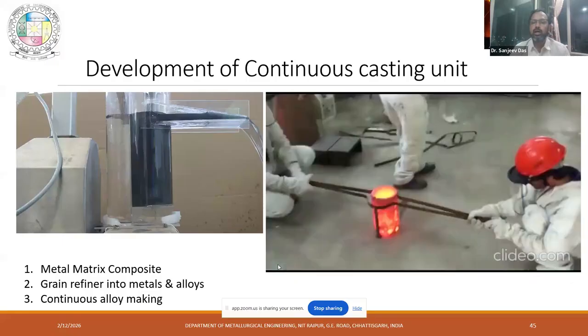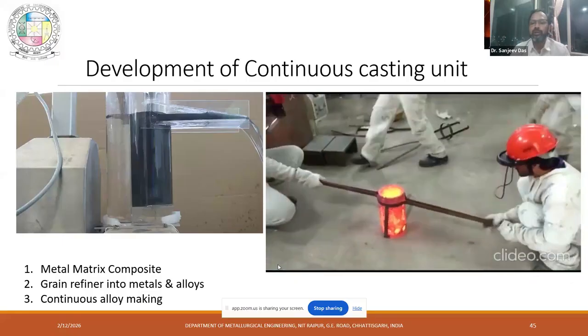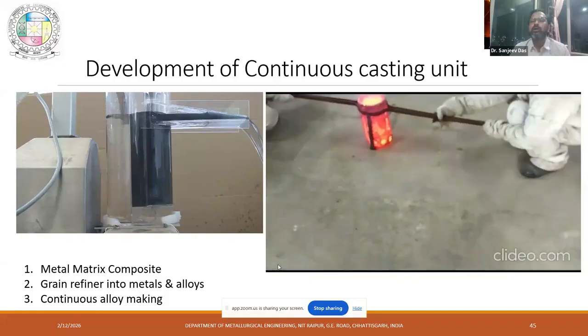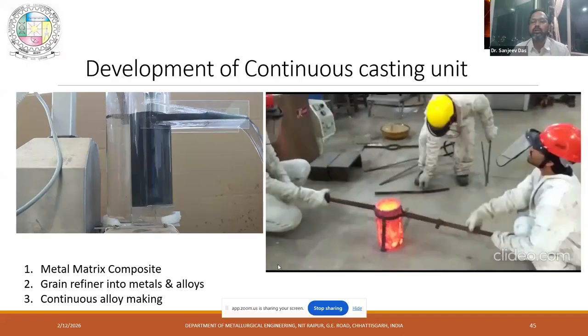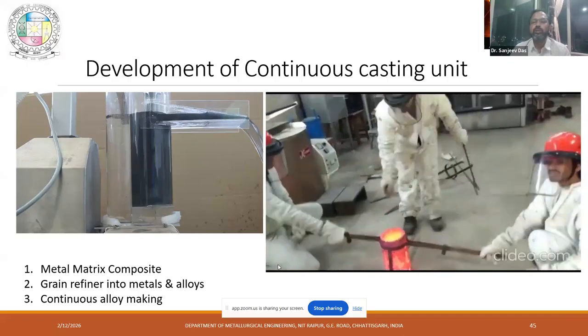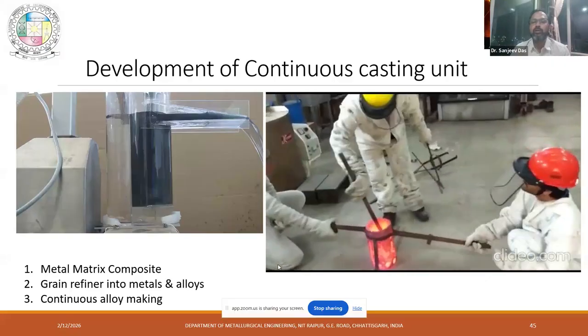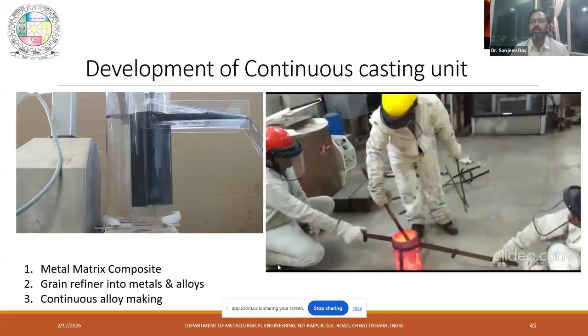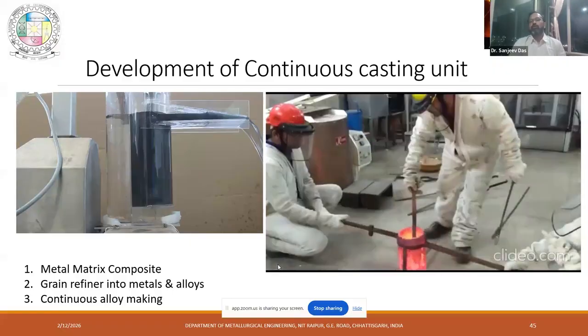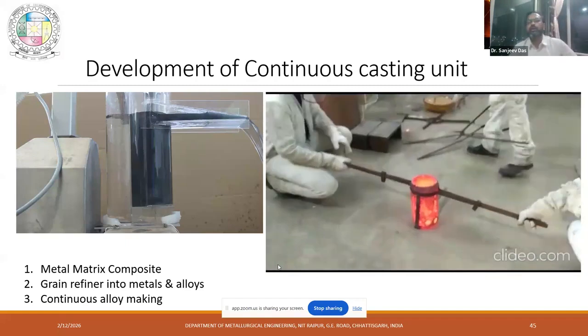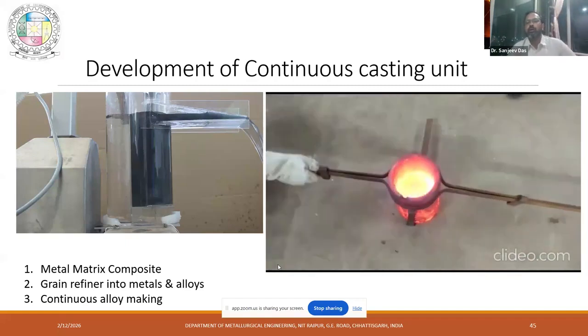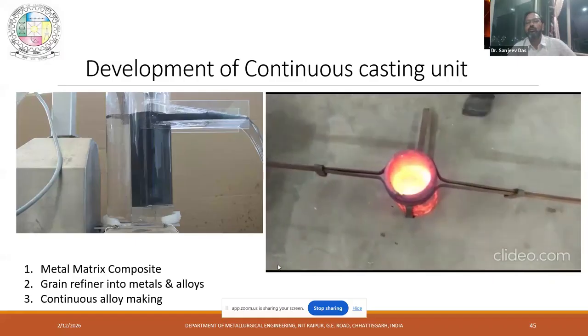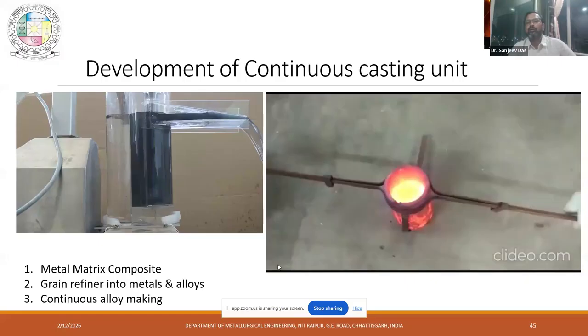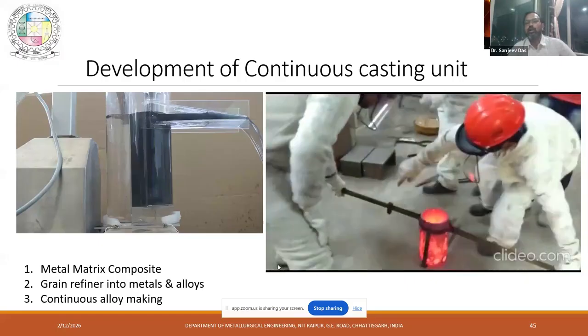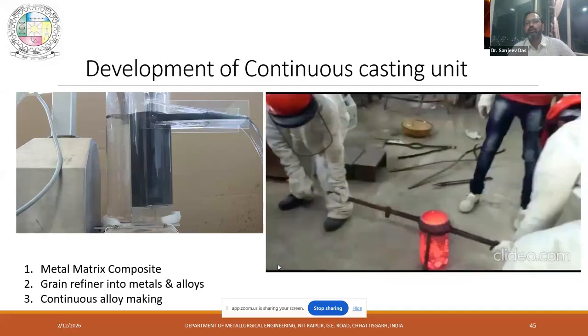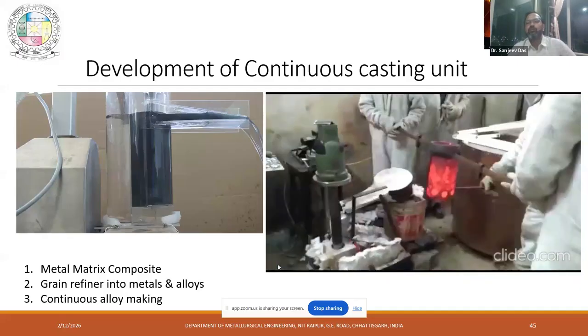It's pretty hot. All these tongs and everything we have designed as per our requirement. The other students are undergrad students who are working on it. So when we do this experiment, first of all, when you take out any liquid metal, you have to take the dross out, because there will be a dross forming on the surface, which is basically aluminium oxide or any other impurity which will float at the top. So basically we remove that from the top surface. Now we have almost clean liquid metal. In industry you can also do degassing. We are not doing degassing because this is a lab scale experiment and we wanted to validate.